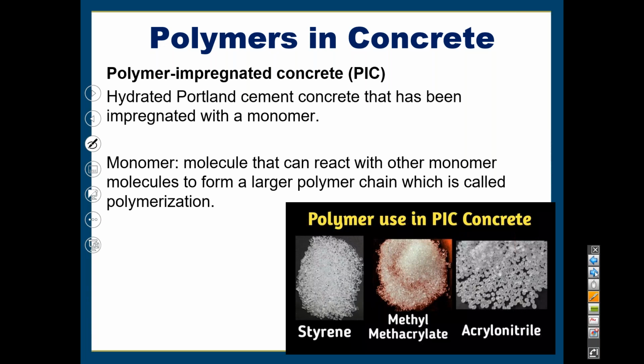Once you do that, then you have to do the polymerization, which is done through a couple of different means: thermal catalytic and promoted catalytic. I'm not going to get into the details of that, but that's another stage that has to be done using one of these materials. It's usually methyl methacrylate that is very often used, or styrene, or other products. But what ends up happening after you do the polymerization is you fill up those voids with this polymer, and it provides for a very strong but also very, very durable concrete.